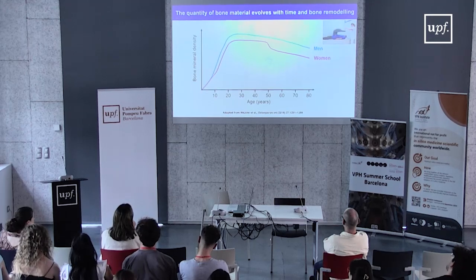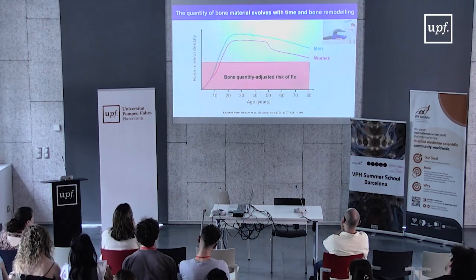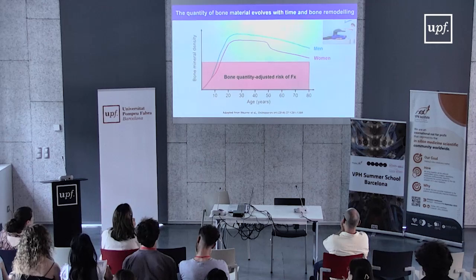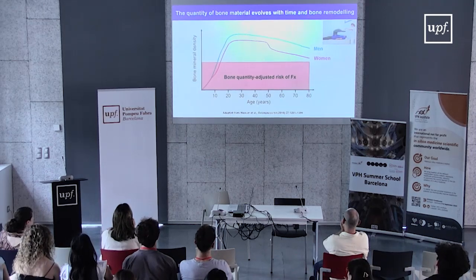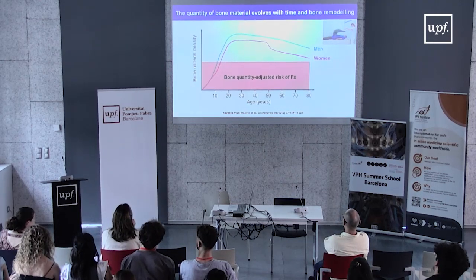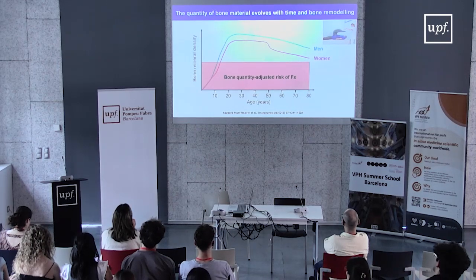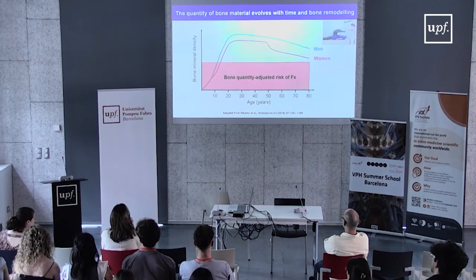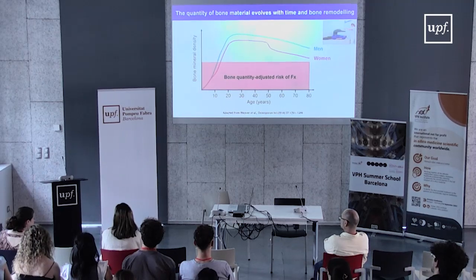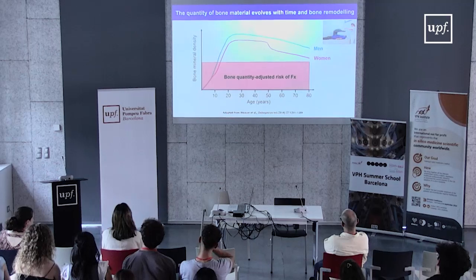This is not really a huge problem as soon as you are not reaching this red square. The problem starts to appear when your quantity of bone is too low to sustain all the stresses that appear on the bone material. And this is what we can measure clinically with a densitometry or osteodensitometry, and we have a clinical score, which is called the T-score, that we will measure, and when you reach 2.5 standard deviation below the normal population, it's when you start to enter this red zone, and that you're at risk of developing a bone fracture.